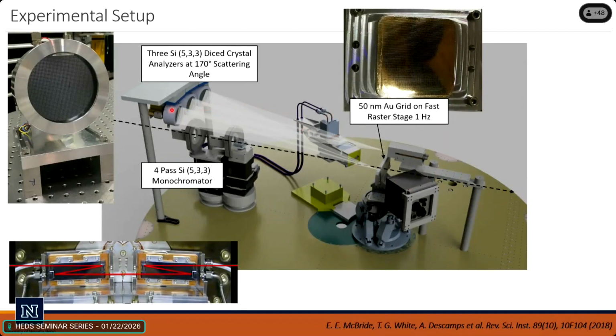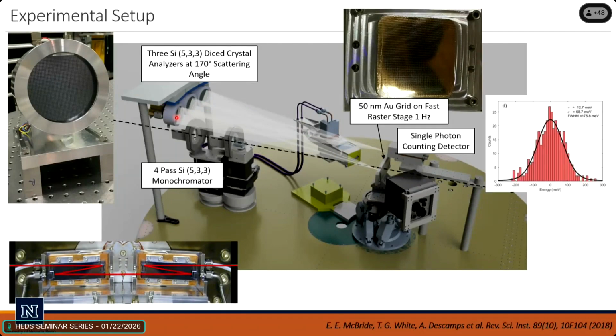They keep a very high resolution in the spectrometer. They sit here a meter away from the target. And so you can see that the solid angle they cover is small, they're about 10 centimeters wide, a meter away. So we're losing some photons there too, okay? And at the end of the day, they scatter or diffract onto a detector here, and that's our spectrometer. As the X-ray energy changes, because the atoms are moving, the position where the X-rays land changes on the camera. It's just Bragg's law, right, to do that. And then we get this broadened spectrum from this hot sample.